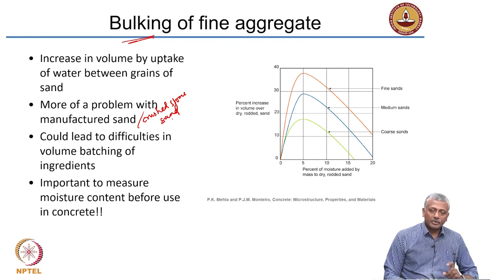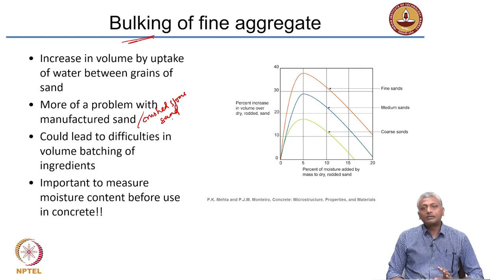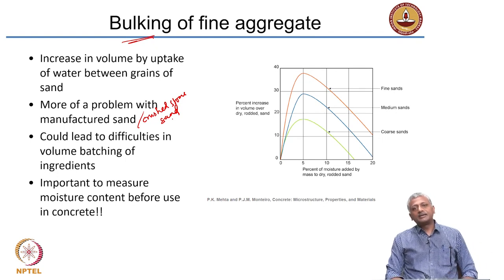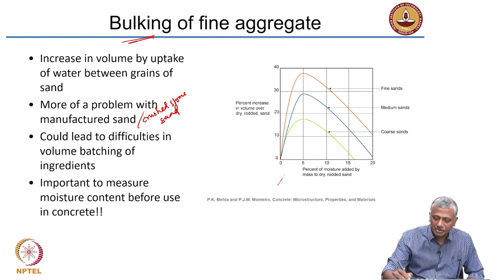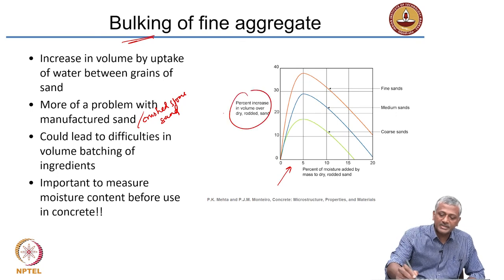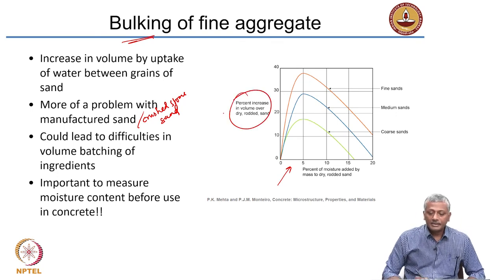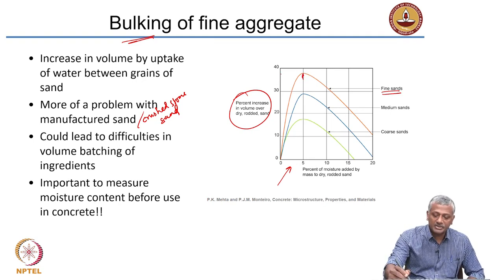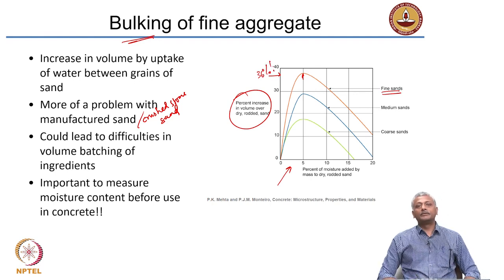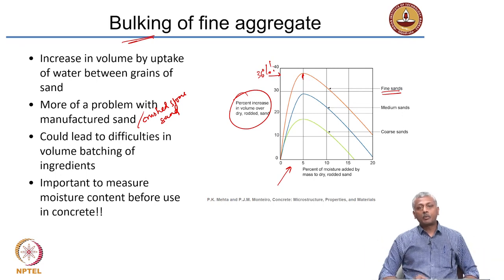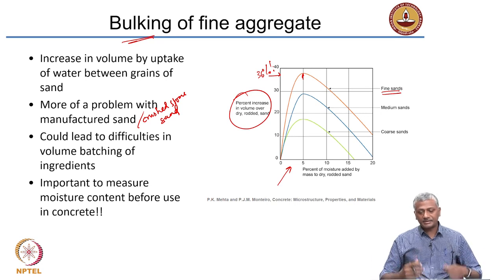It is important to measure the moisture content of the aggregate in concrete because that ultimately leads to a lot of hassles at the job site. A picture from a textbook on concrete technology shows that bulking or percent increase in volume is most affected for fine sands — the increase in volume can be as much as 35 to 36 percent. So if you think you have one cubic meter, it is actually 1.36 cubic meters because of the water getting inside the fine sand.